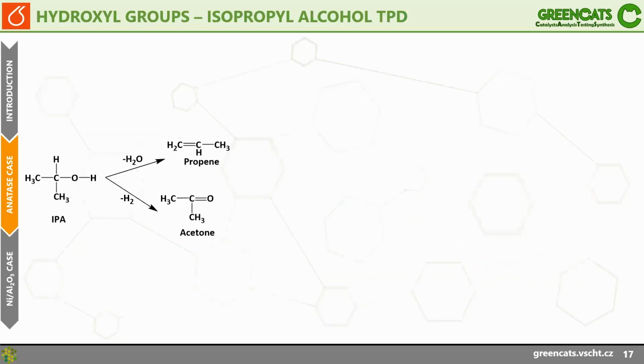and behave as Lewis acids. As a second method for probing the surface, we used the adsorption of isopropanol. The motivation was a little different: we were preparing at the same time materials combining silica and titania, and we were after distinguishing those two. The OH groups in silica and titania should be distinguishable because of the different desorption maxima with the temperature of the maxima here.